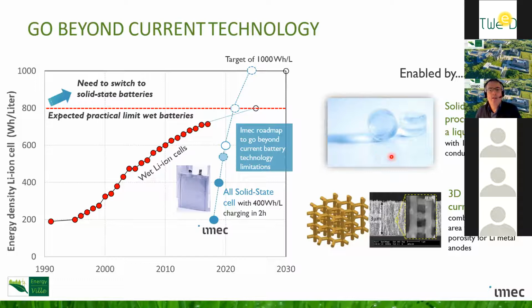And although it's a solid material, it has a high conductivity at room temperature of about 10 millisiemens per centimeter, which is actually already similar and slightly better than the ion conductivity of wet batteries. And this is because it's kind of a solid liquidified material that we use. Another important element is this 3D nanomesh structure, which is a very dense mesh with a high surface area that is then coated with this electrolyte, and in this way gives you a very high surface and a high dense material that gives us this high energy density. And we use this for the cathode and then with lithium metal on the anode.